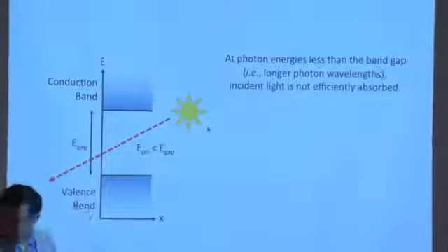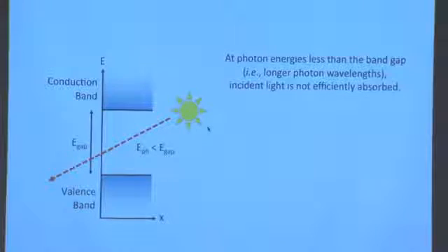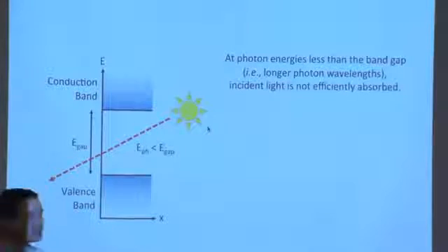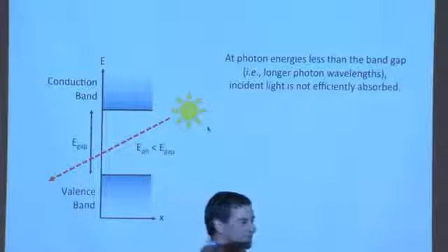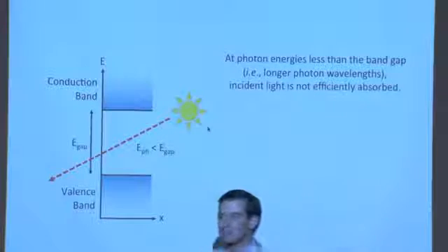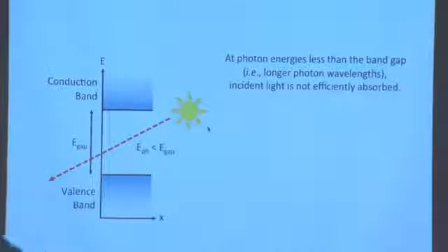Now, silicon, much smaller bandgap. And in the case of silicon, even the visible gets blocked. So silicon would make a really crummy window. But it makes a really great infrared window. So if you're detecting infrared light and want to block out all the visible, you might consider sticking up a filter made of silicon. And that's regularly done in laboratories.